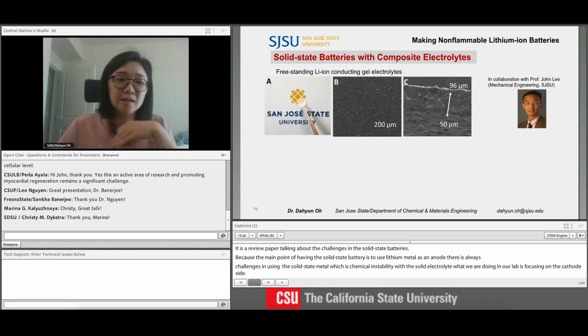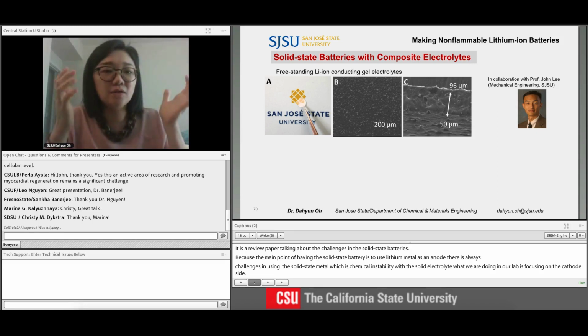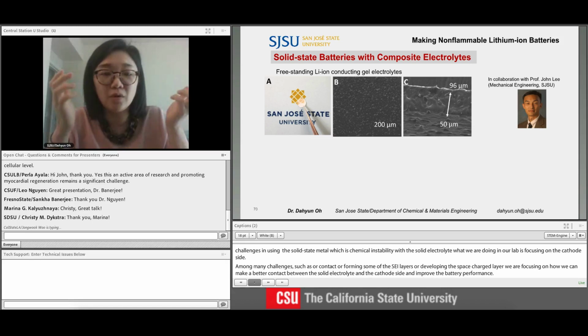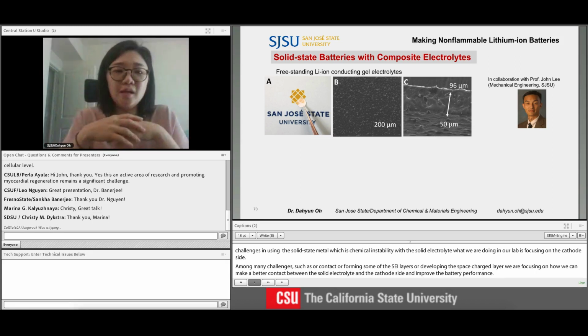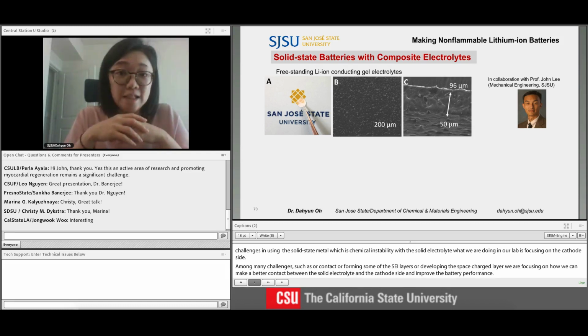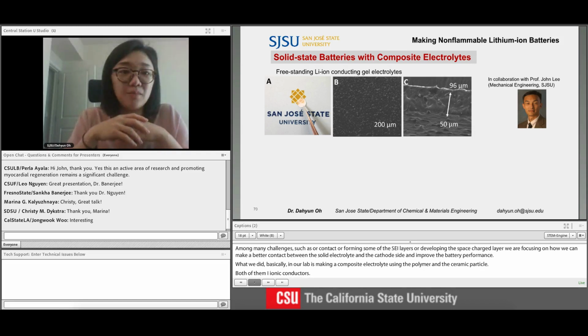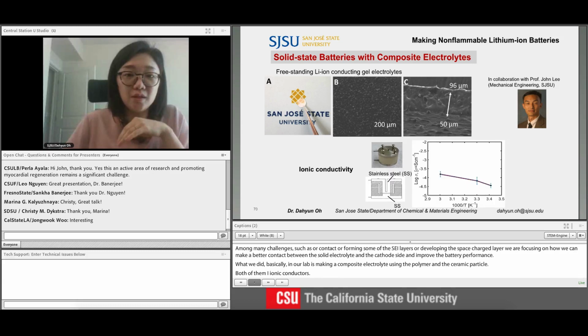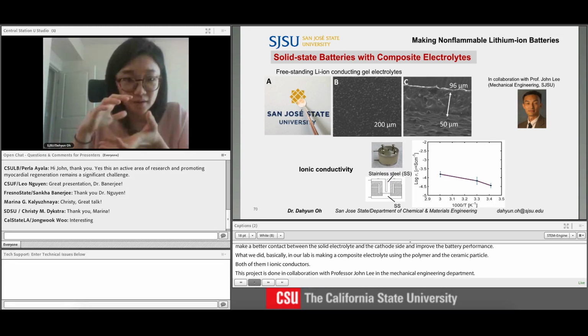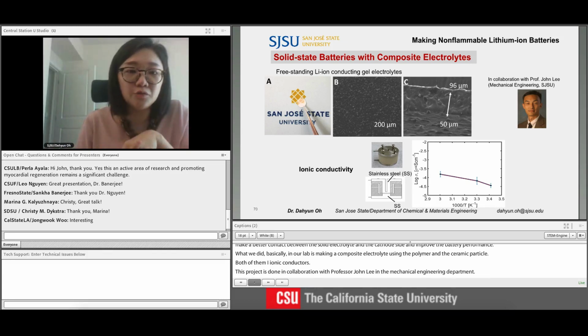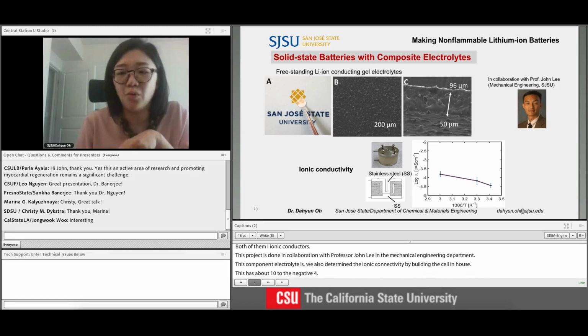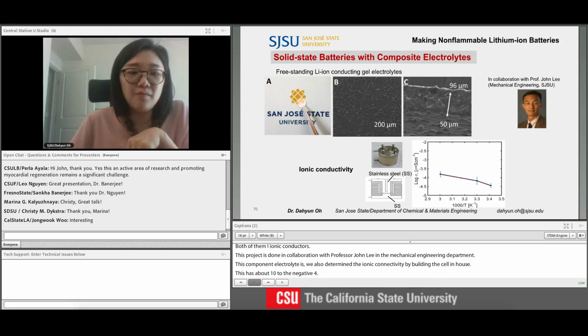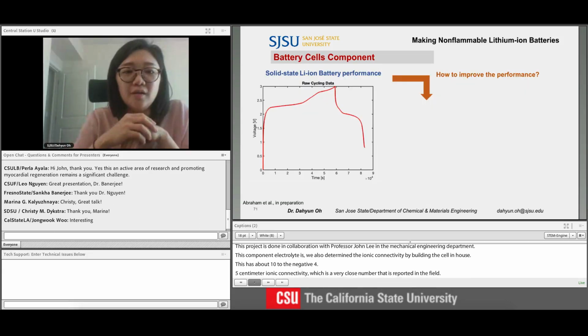So what we did basically in our lab is making a composite electrolyte using the polymer and the ceramic particle, both of which are ionic conductors. And this project is done in collaboration with Professor John Lee in the Mechanical Engineering Department. We also determined the ionic conductivity by building the cell in-house. And this has about 10 to the negative 4.5 Siemens per centimeter ionic conductivity at room temperature, which is very close to the numbers reported in the field. So with this solid electrolyte, we tested the full cell batteries, and it seems like it's getting some capacity, but we're not fully happy with that.